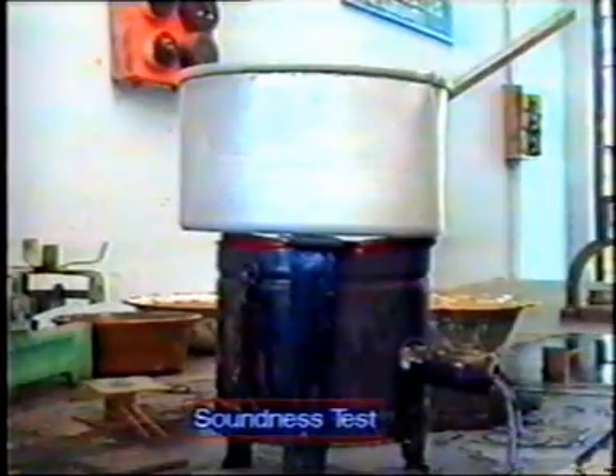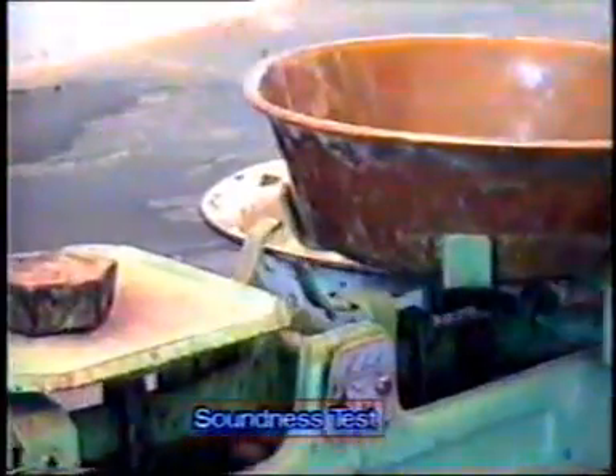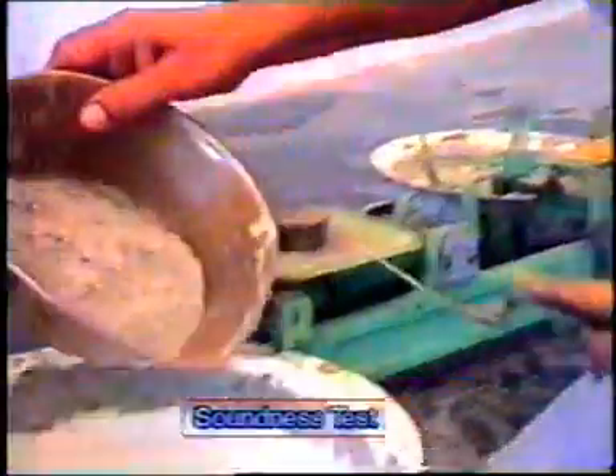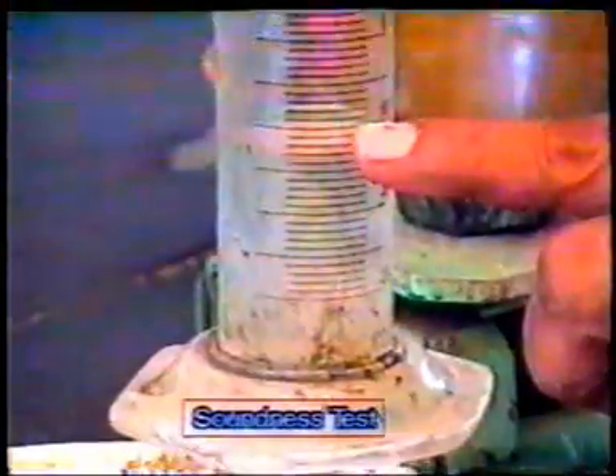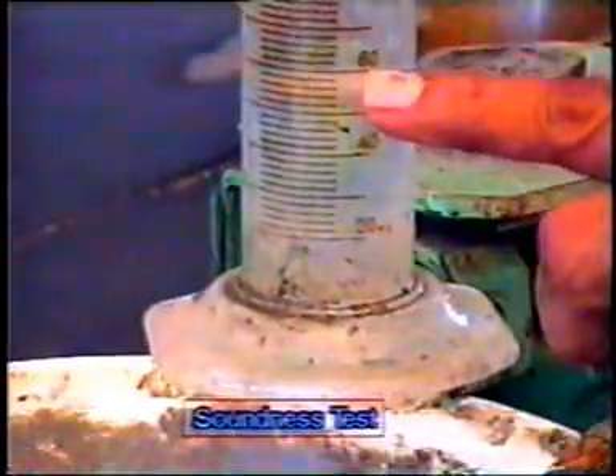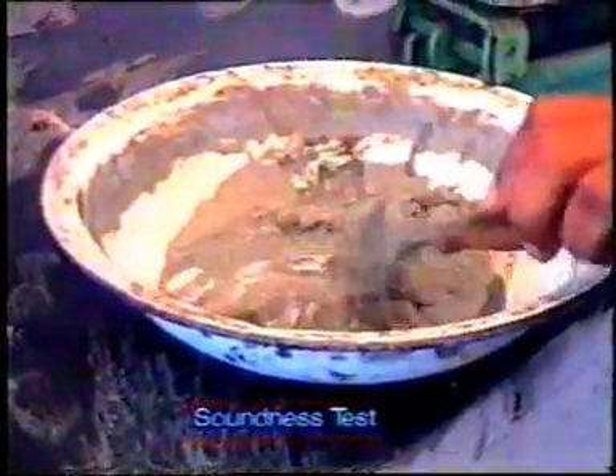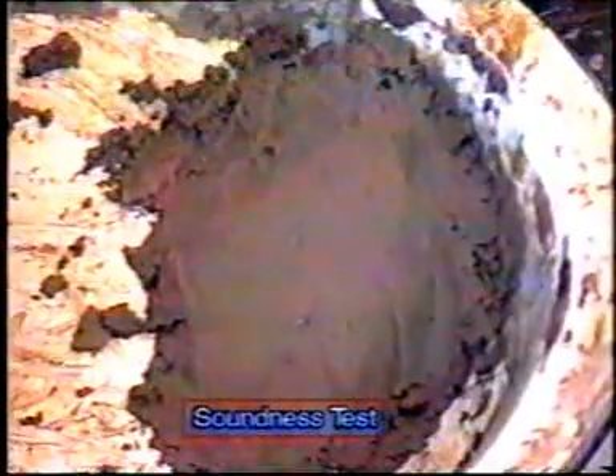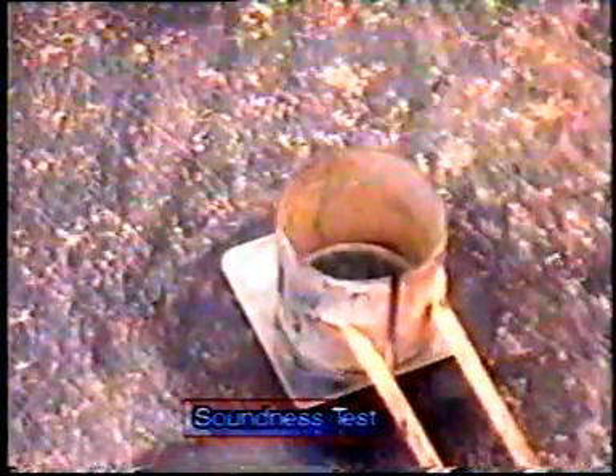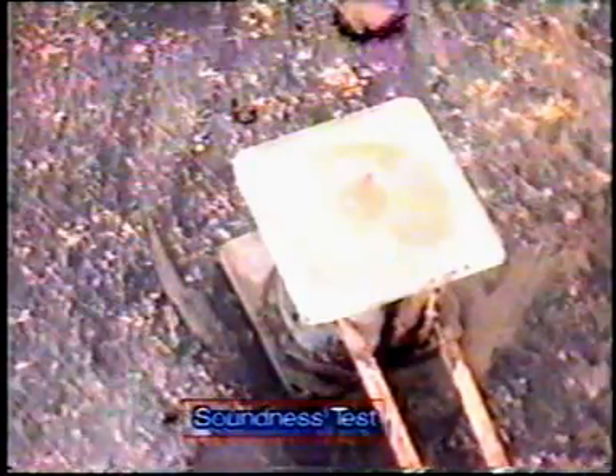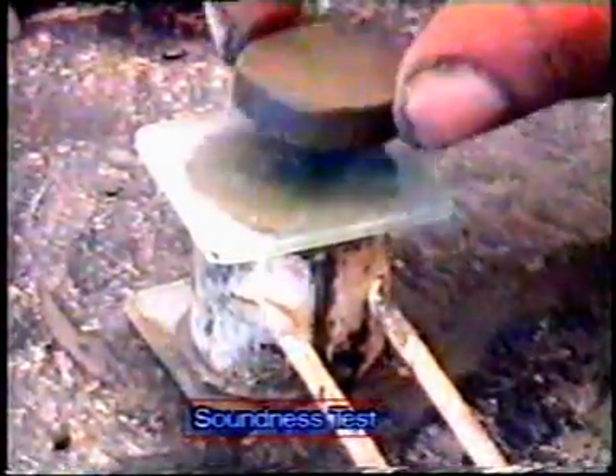Now let us see the procedure. Take 200 grams of cement into the mixing dish. Add 0.78 times the water required for the normal consistency. Mix it thoroughly to get a uniform paste. Put it in the split cylinder which is placed on a glass plate, taking care to keep the indicators together during this operation. Cover the cylinder with the glass plate and place a small weight on the glass plate.